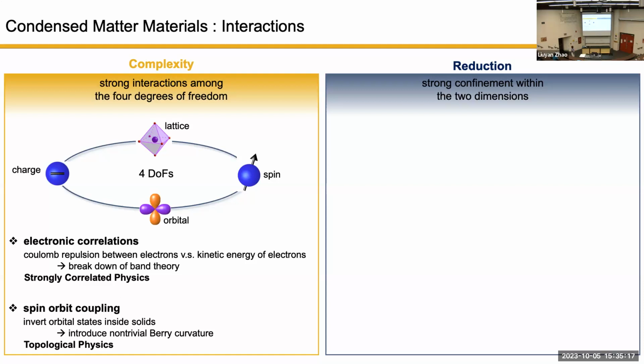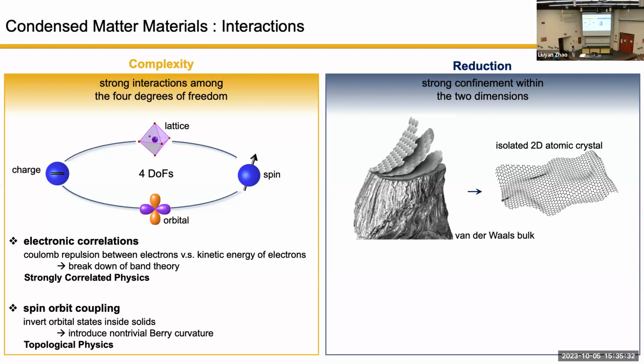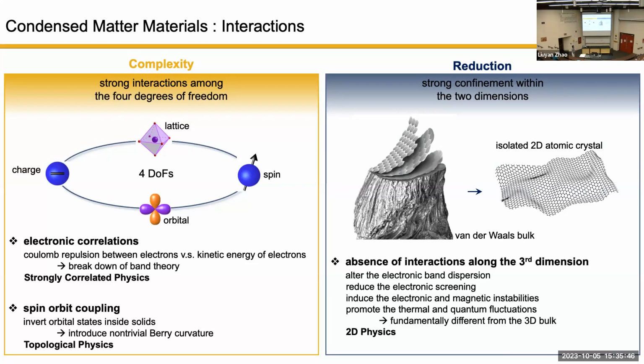So you can see that the two types of interaction in the complexity family are going to lead to either strongly correlated physics or topological physics, which are two main threads over the past few decades in three-dimensional materials. In contrast, in the second family, where we care about reduction, it really started by people's ability to isolate monolayer graphene out of the bulk counterpart. So now you have a nearly freestanding atomically thin material. By doing so, we get a few benefits. Once it's very thin and it's just one layer, your band structure gets changed, meaning that your electrons' energy versus momentum dispersion relationship gets changed from the bulk counterpart. Graphene is a fantastic example in this sense, because bulk is a massive electron, while monolayer is a massless electron, okay?